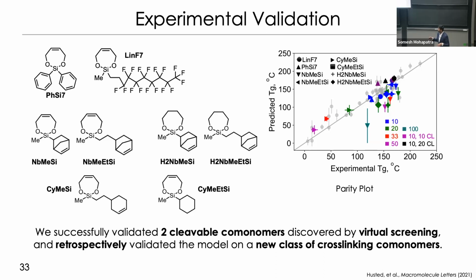And while we were doing this work, the Johnson lab had started working on a class of cross-linking co-monomers, and we retrospectively validated a whole bunch of these molecules which the model had never seen onto the data set. And we found that the model is able to capture well enough for some of these cases, except one. And looking back on NBMESI and seeing why the model is not able to do so, we found out that the model had always had some amount of polydicyclopentadiene in it. There was never a condition when a co-monomer was 100% or a cross-linker was 100%. While in this particular case, the model was seeing for the first time a cross-linking co-monomer that was 100%.